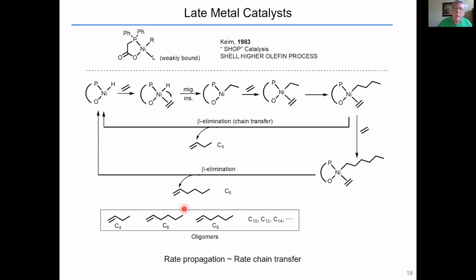So to skip ahead, well, no, I should not go too far. So we decided to think about other late metal systems. And if you go to the literature, you find that in the early 80s, Shell developed a so-called SHOP process in which they used a neutral nickel system to oligomerize ethylene and make a series of alpha olefins. The fact that we generate alpha olefins here means that the rate of propagation is roughly the rate of chain transfer. So we don't get polymer, but we do get more than dimer. And these alpha olefins are quite valuable as precursors to detergents and oil additives and so on.